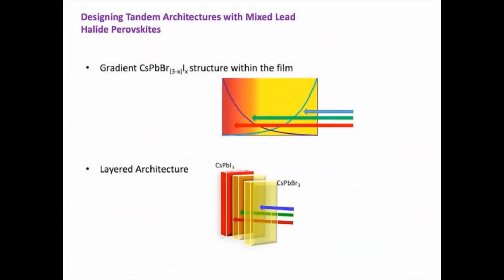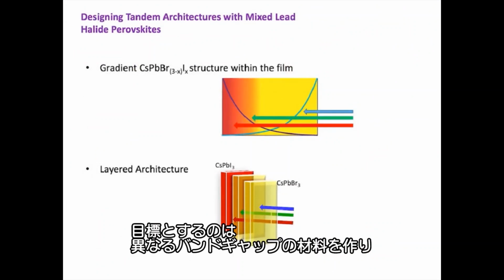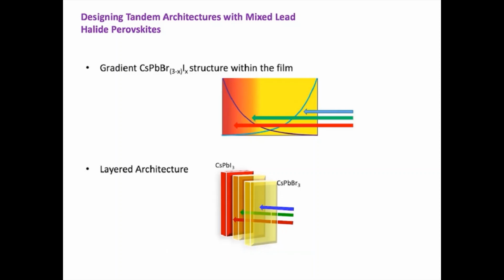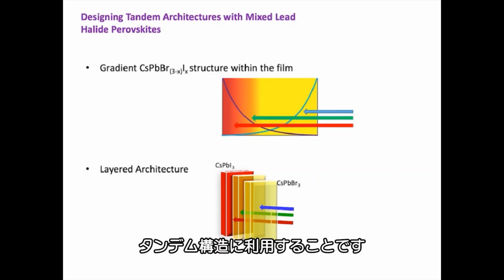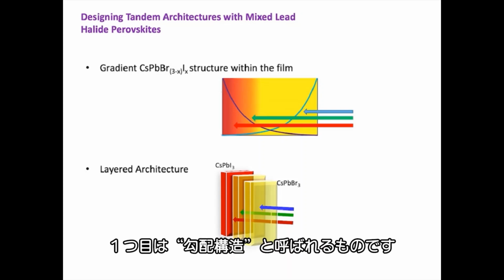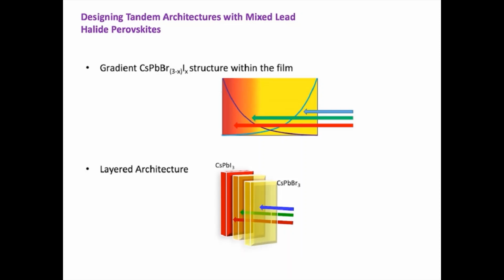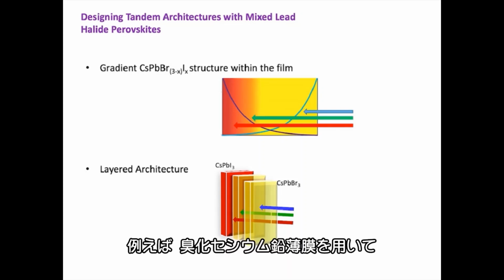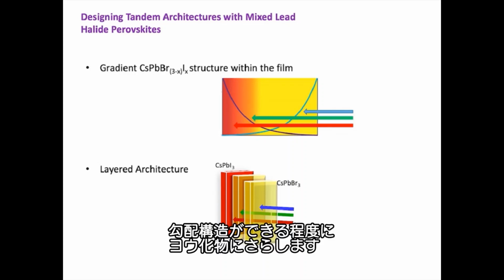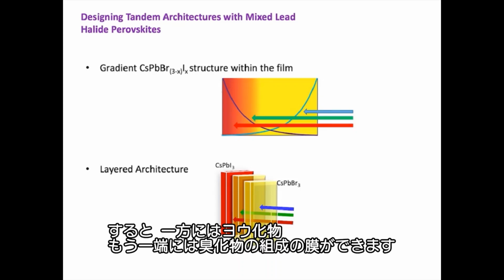So there are various techniques people use to make it. The goal is to make different band gap materials so that one can use them in a tandem architecture. So there are 2 ways of doing this. One is what we call gradient architecture. Say for example you take a cesium lead bromide film and expose it to iodide just enough to get a gradient structure. So at one end you have iodide, other end you have bromide.